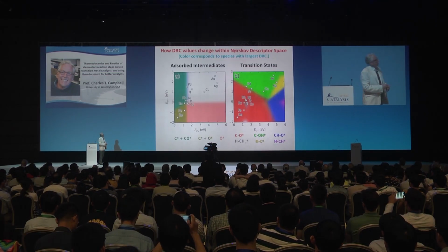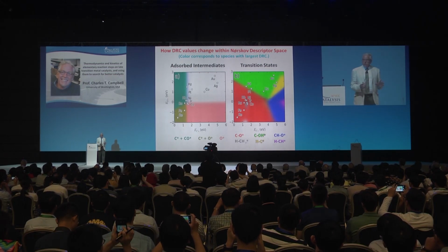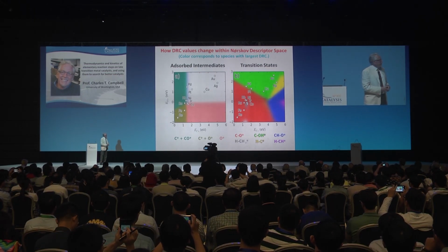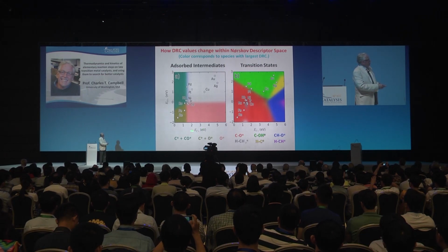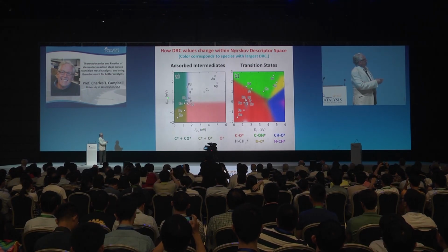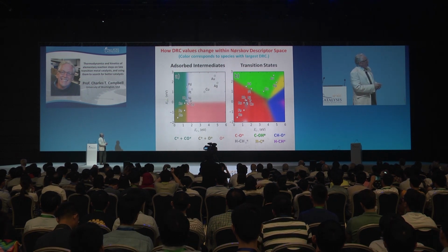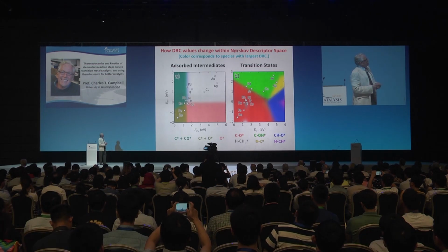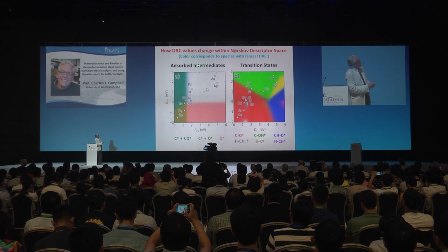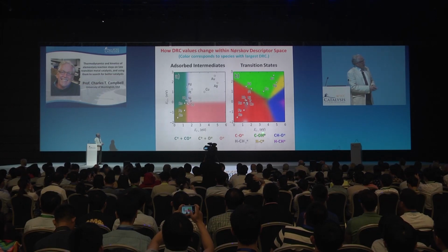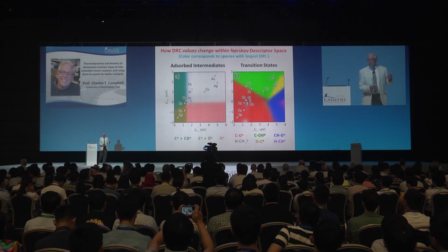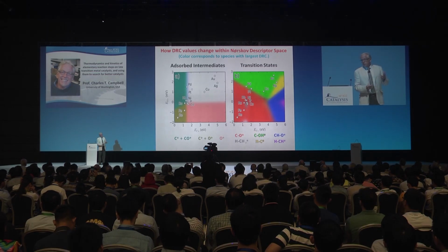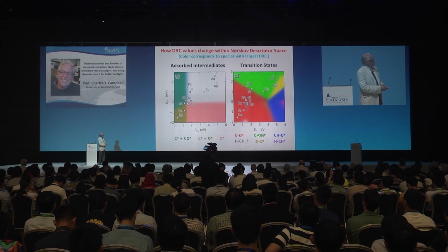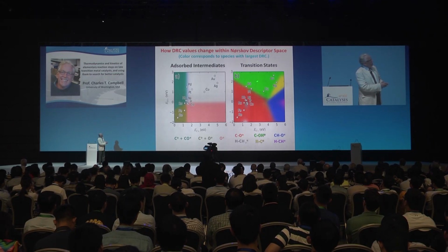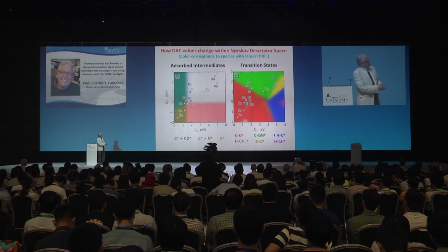And so this is a plot to try to show how the degrees of rate control depend on the nature of the material. I've resorted to Jens Norskov's descriptor space for this reaction, the binding energy to oxygen and carbon for the materials. And here's our reference material. And these colors, these are for intermediates and these are for transition states. The colors refer to when that species has a high, almost unit degree of rate control or a -1 degree of rate control. For example, in this region, breaking the carbon-oxygen bond is the rate determining step.